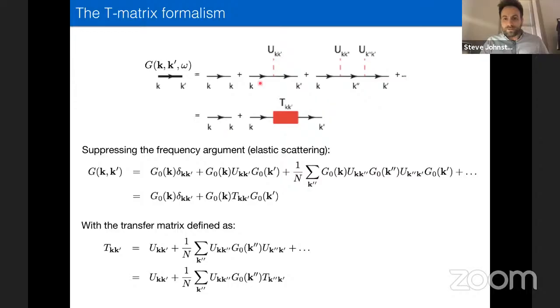You can turn this into equation form just following Feynman rules. So you wind up with a self-consistency equation like so, where you relate the dressed Green's function to the bare Green's function plus this T matrix. And you also get a secondary self-consistent equation, which involves the T matrix on both sides plus your impurity potential. So the idea is, if you know this impurity potential, you can calculate this self-consistently, get the T matrix. Once you have that, you can put it into here and you can get the Green's function. And that's basically all we do at this level of modeling.